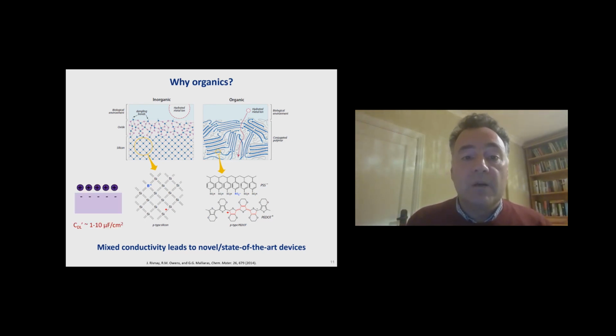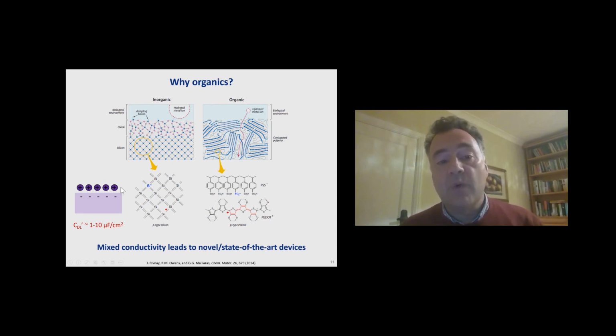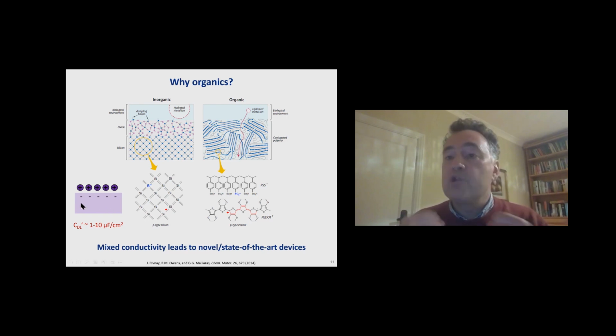Even if you could remove this oxide layer, and use, for example, a noble metal such as platinum, you would arrive at a situation where you would have ions on one side of the interface in the brain, and then electrons on the other side of the interface in your platinum electrode. And this coupling along the interface is fairly weak, and it's characterized by what is called the double layer capacitance. It's a fixed value, and it just limits how strongly these two carriers can interact with each other.